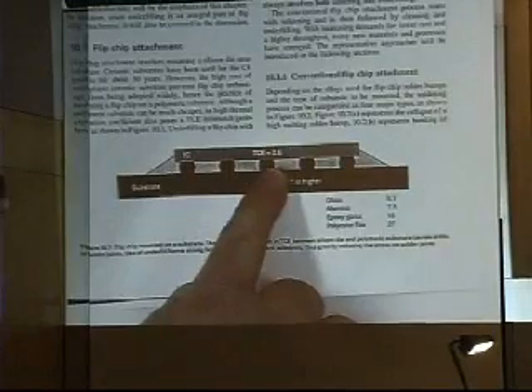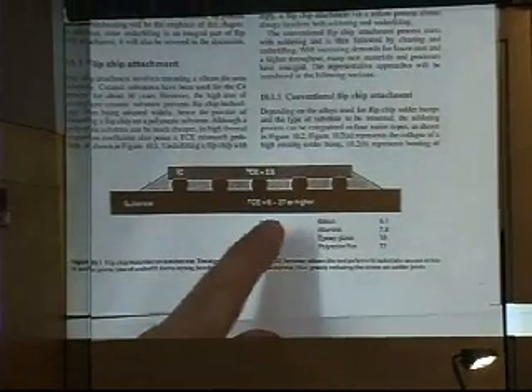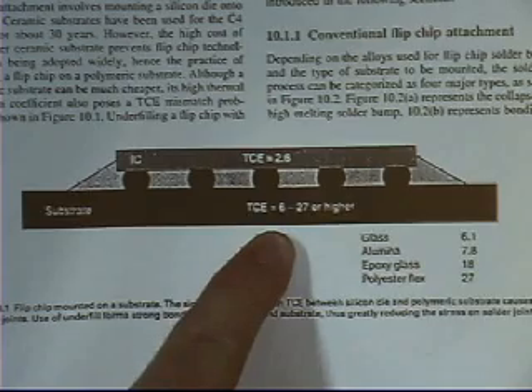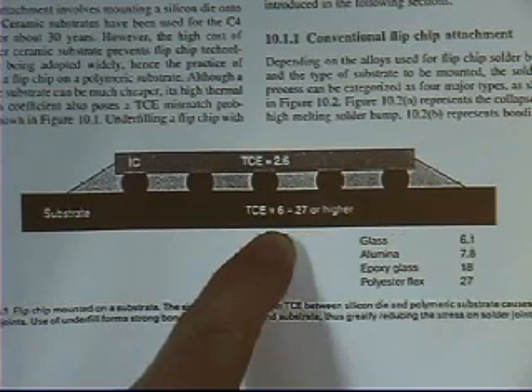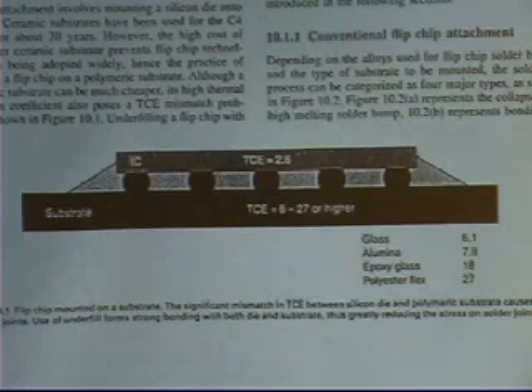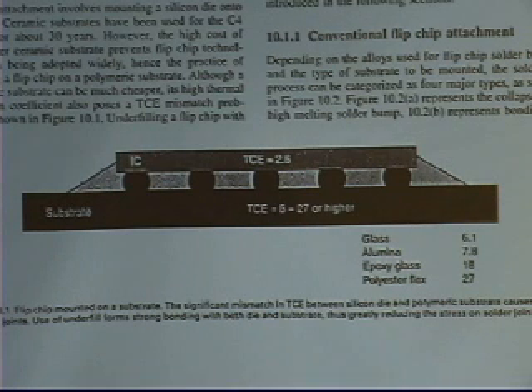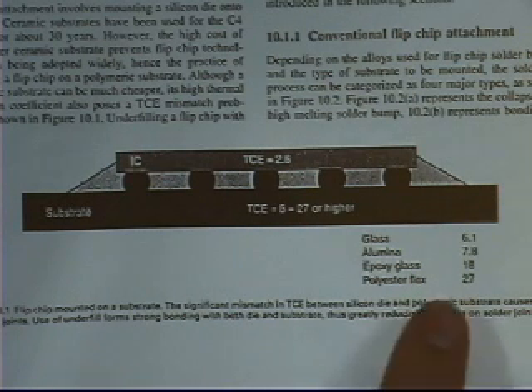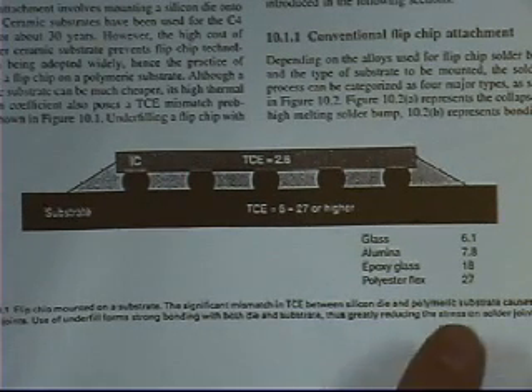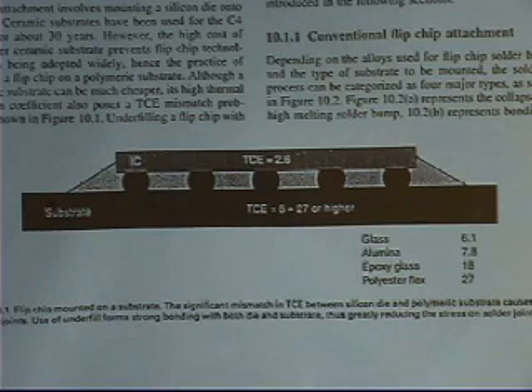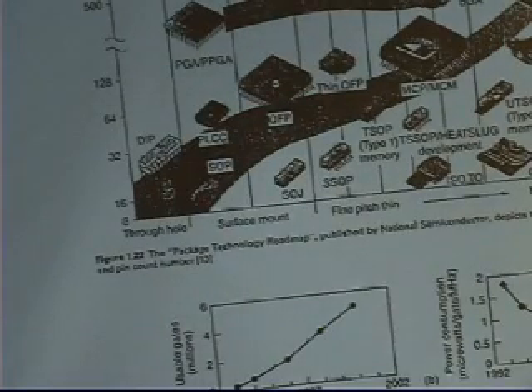If I look at the integrated circuit, it has a coefficient of thermal expansion of 2.6. The substrate will have, depending on whether it's aluminum nitride or copper or whatever, a coefficient of thermal expansion of 6 to 27. And here are some other materials: glass, alumina, epoxy glass, polyester flex. Actually, 27 is polyester flex. So these are the different types of substrates that you might put your integrated circuit on. And the problem is these things heat up 30 degrees centigrade, or more and more.